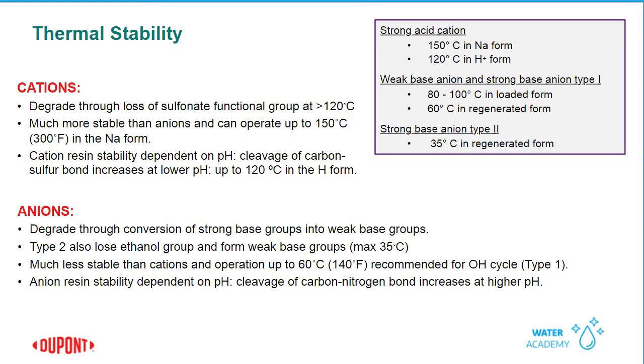However, if you do happen to have some excursions that you know are going to occur and are going to be higher than this, then for strong acid cation resins, for example, there are some things that we can do, like recommend a more oxidatively stable resin. So something with higher cross-linking, maybe a 10% gel resin instead of an 8% gel cation resin. Or in some cases, we might move to a macroporous resin depending upon the level. So consult with your tech service ion exchange person if you think you're going to have excursions higher than our maximum, to make sure that you're using the right resin for your level of oxidation.